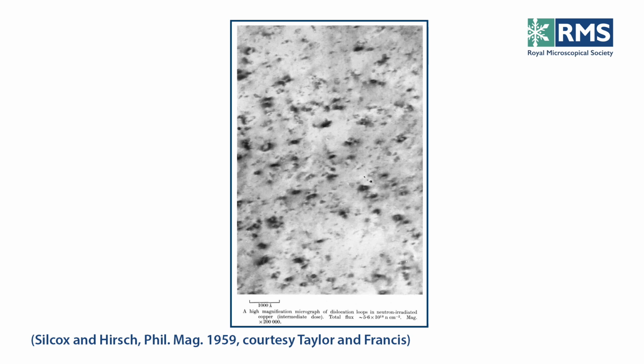Now, at about this time, there was quite a lot of activity about developing nuclear reactors. And one of the problems was that the pressure vessels in the pressurized water reactor became embrittled as a result of the damage by neutron irradiation. And this technique provided a means of actually studying what the nature of the damage was. And by some coincidence, the technique was developed just about the right time for it to be used. And this next picture shows you the sort of thing that you see in neutron irradiated copper.